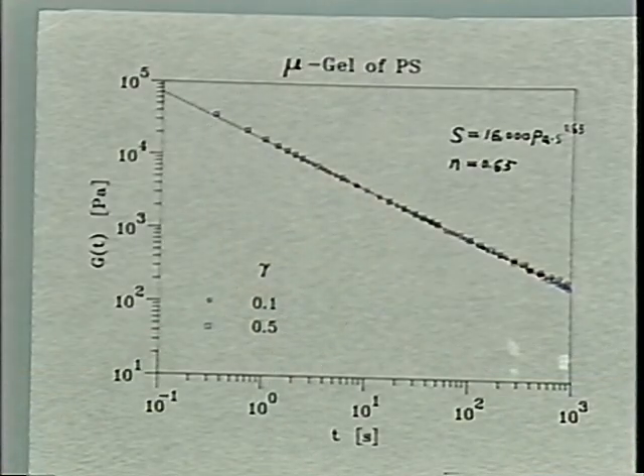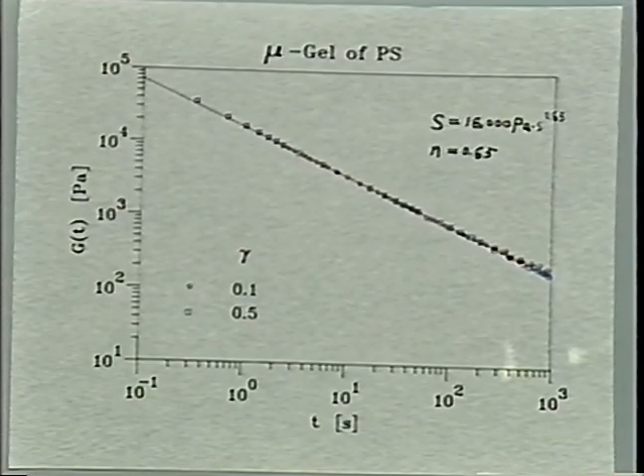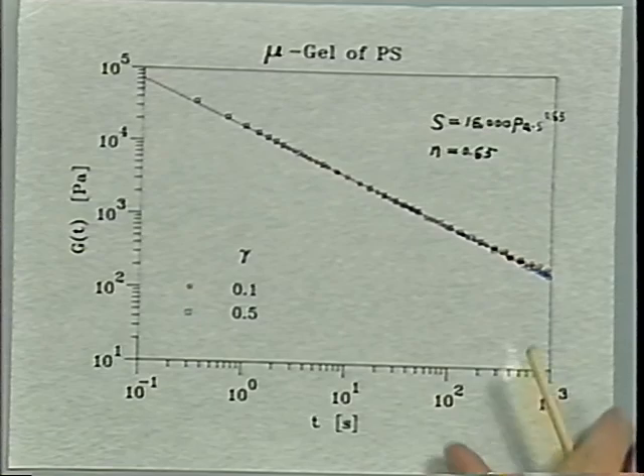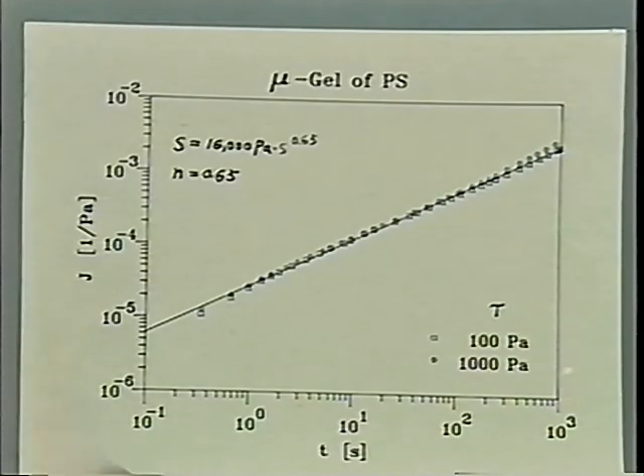Wait a minute. We have now G prime, G double prime in a power law. This is the modulus now, the relaxation modulus, again following a power law. And Yigang also did creep experiments of the same system. And this also follows a power law. And the dotted line comes out of modeling calculations.